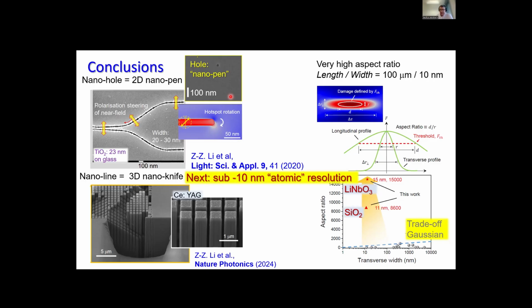Yeah, so this is on the slide here. It's 15,000. This was for lithium niobate inscription, while the slicing of silica was close to 9,000. So the width is in tens of nanometers, but the length is microns. You see here on the top, the Bessel beam was defined for the focusing we had. It was 100 microns long, and the modification is around 10 nanometers. But when we etch, it's probably larger. It's larger widths. So still you see the very high aspect ratio.